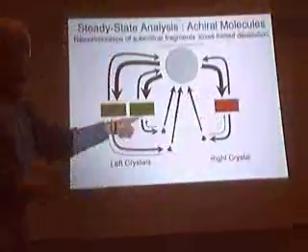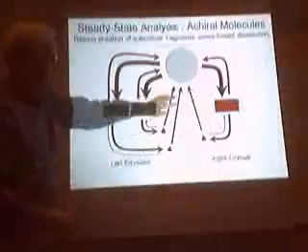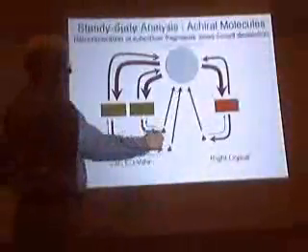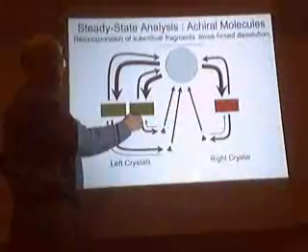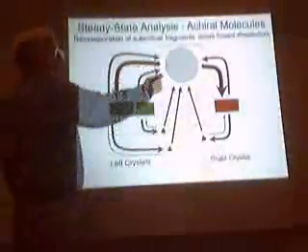Now, the effect of that is to lower the flow through dissolution, because this crystal, which is made at a given rate, either dissolves or is reincorporated. If it's allowed to reincorporate, that reduces the amount of material that goes here. It reduces the concentration here. It reduces the flow back. But again, everything is the same between the two crystals, except